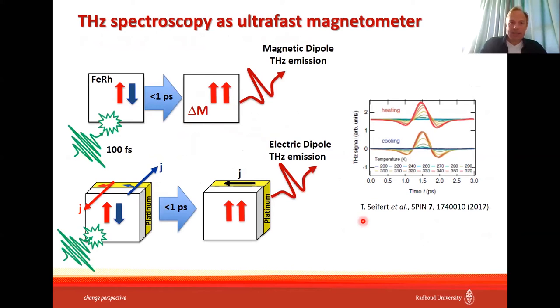Again, people realized that THz spectroscopy can be a very efficient and ultrafast magnetometer. And the first work published on this topic again came from Kampfrath's group and in a big collaboration. I will come to this in a moment. And they saw indeed that there is a very fast increase of the magnetization in the medium, which is seen as a THz emission. So they pumped iron rhodium with platinum on the top with a short laser pulse, and they saw that under the influence of this excitation, THz radiation is emitted.